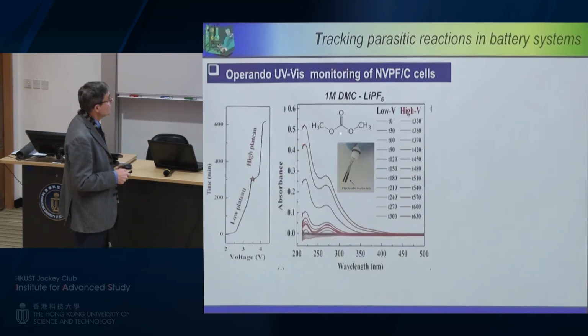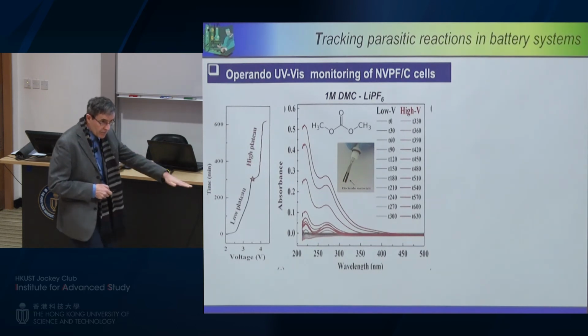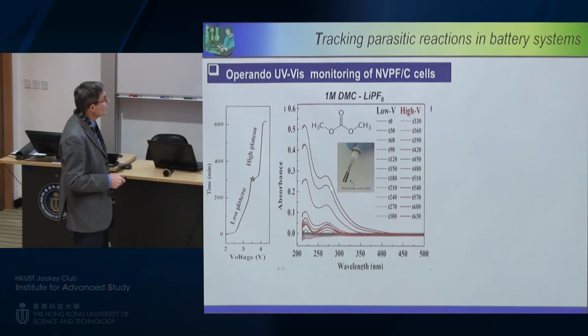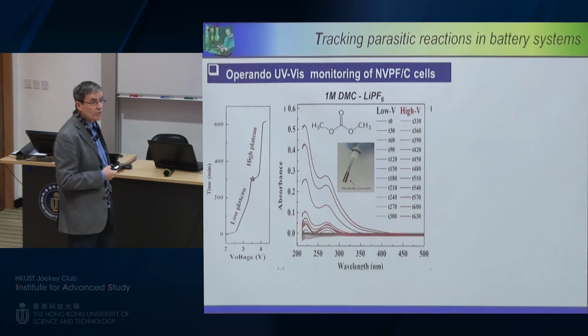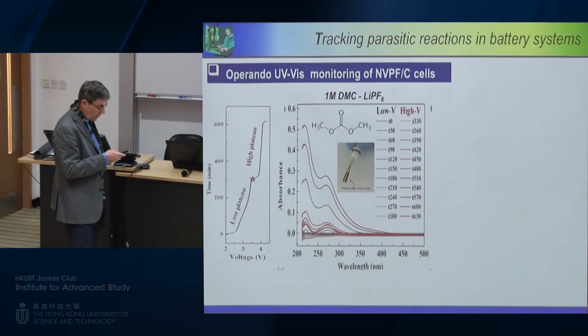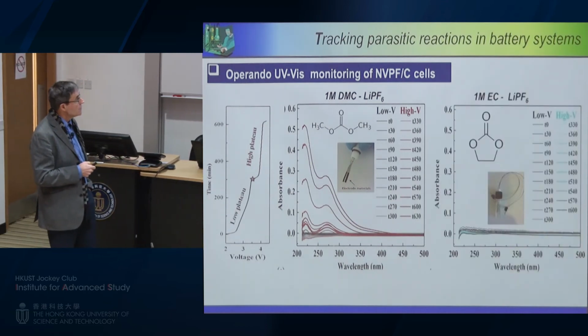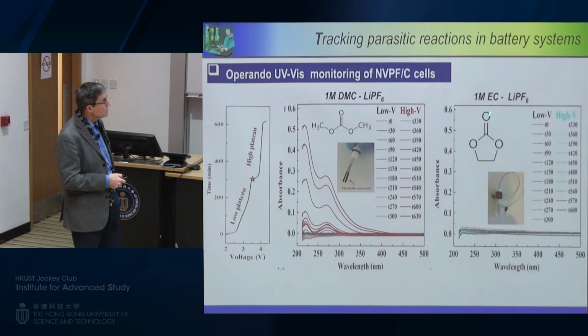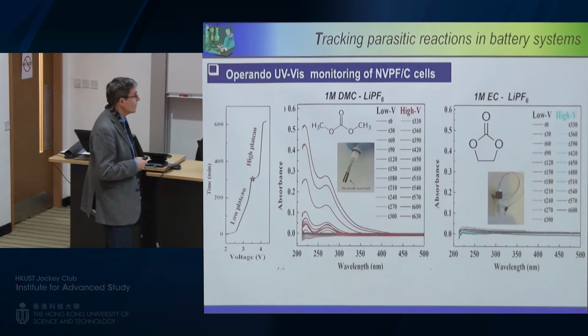So we tried to go back to the electrolyte and to sort out what's the problem by separating each electrolyte. So we look here at this linear carbonate, and you can see here, as soon as we go to the high plateau here, which means that here you are on the negative reducing of the carbon, we see that there definitively we were releasing parasitic reactions. We look at the same experiment with ethylene carbonate. Here, the good news, nothing was happening.